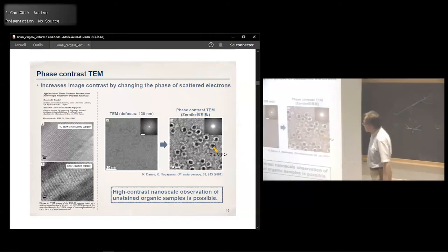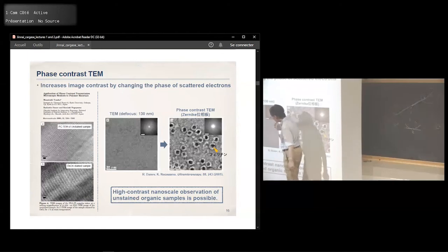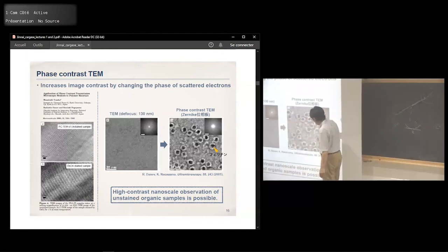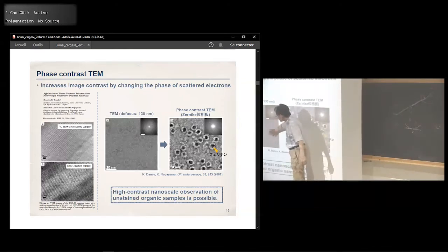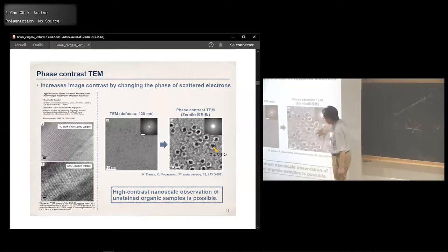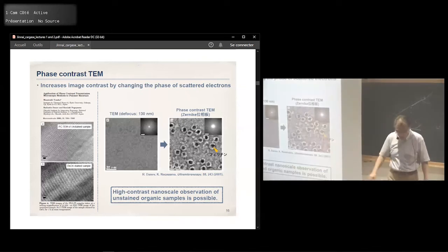And this is the experimental result. This is a phase separated lamellar structure of polymers, and this is an osmium stained sample. You can see the lamellar structure here, and this is the unstained sample with the phase contrast. You can see the structure here. This is another example, some sort of spherical domain or particle, and under the conventional setup, it's nothing. But with the phase plate, we have a very good contrast. So that's one way to enhance the contrast.